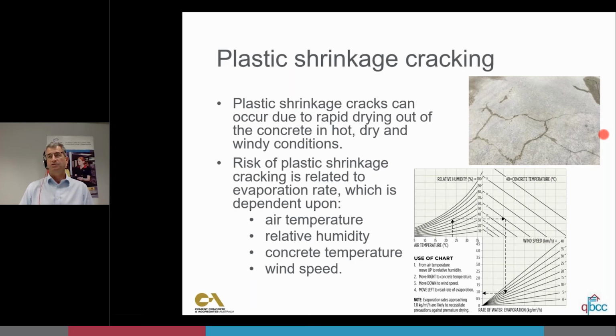We're getting drying of the surface while the concrete is still plastic underneath. So that surface layer is drying and shrinking, and if it's not drying and shrinking underneath, then you're going to get cracking on the surface. That's plastic cracking. To avoid it, we need to make sure that while that concrete is setting, the top remains wet. And that's why bleed water is a good thing. The bleed water rising up keeps that surface wet, prevents it from drying out, and allows it to set with the water and gain some strength.